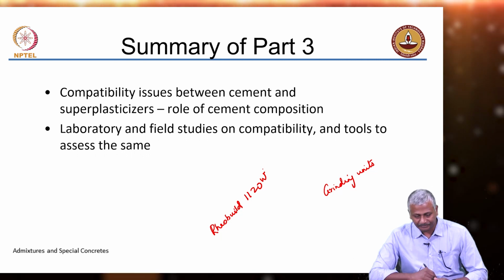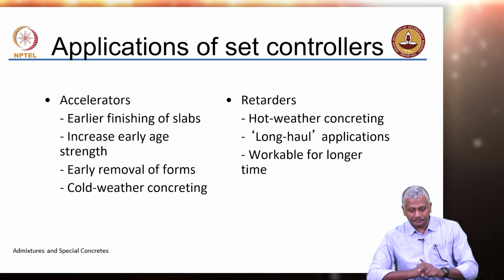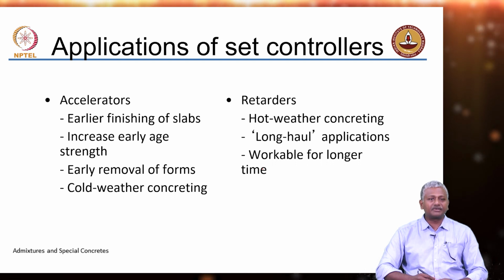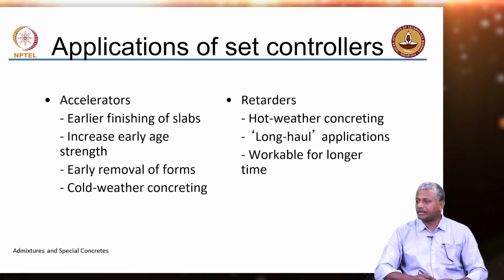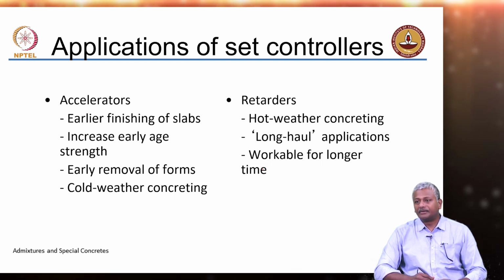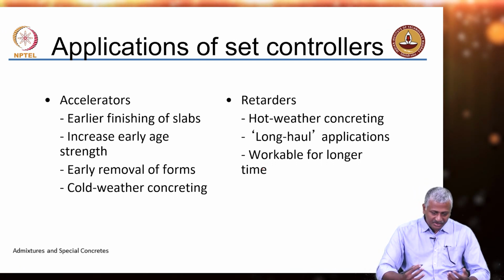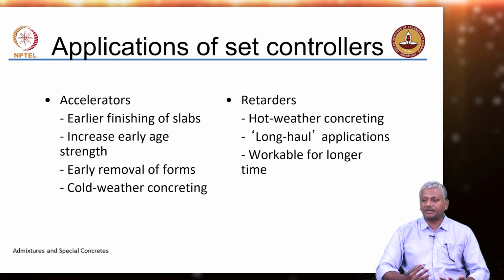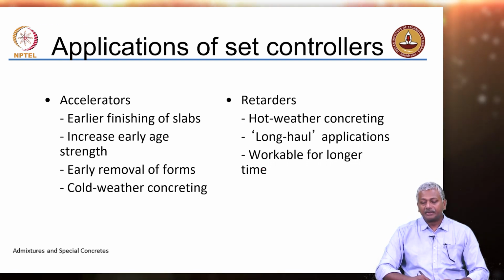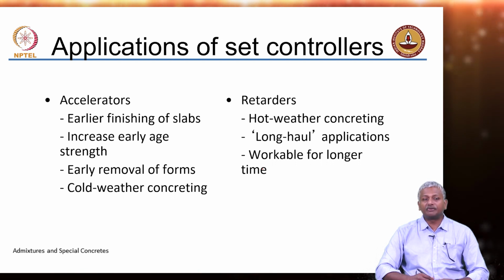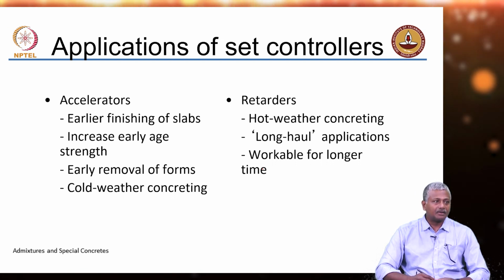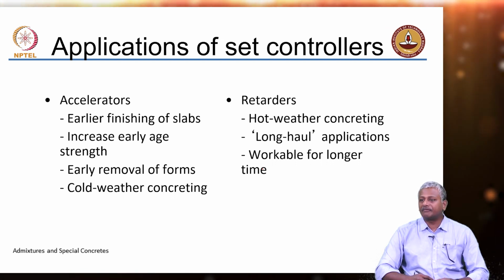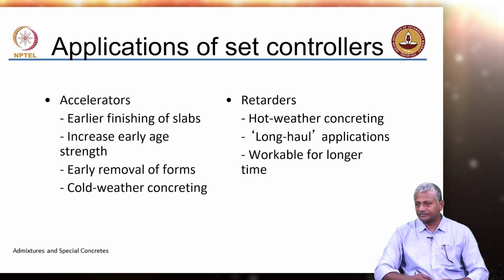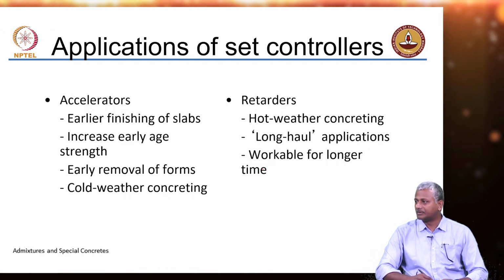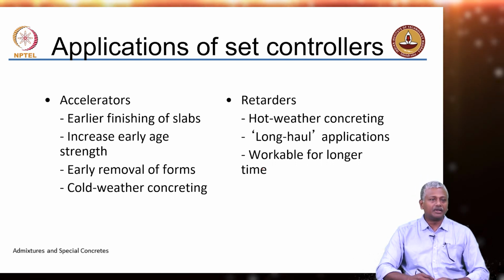Right. Now, in this part of the chemical admixtures chapter, we will take a look at set controlling agents, accelerators and retarders. Now, accelerators obviously are needed when you want early strength, earlier finishing of slabs, early removal of forms, or if you are doing concreting in the cold weather, where because of the low temperatures you may have difficulty in attaining strength fast enough. So, you want to accelerate the concrete mix because the cement reaction is slowed down at low temperatures.